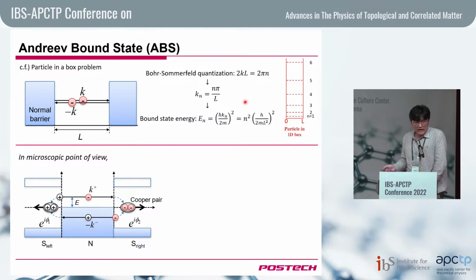And then our Josephson junction can also be viewed as a particle in a box. But now the barrier is the superconducting gap, not just the insulating gap. So if your electron energy is smaller than the superconducting gap, then the electron just cannot get into the superconductor, but it can grab another electron which has the opposite energy by forming a zero energy Cooper pair, so it can get into the superconductor. But it will result in reflecting a hole, because this electron grabbed this electron, so it will result in a hole reflected along the other direction. This is called Andreev reflection.